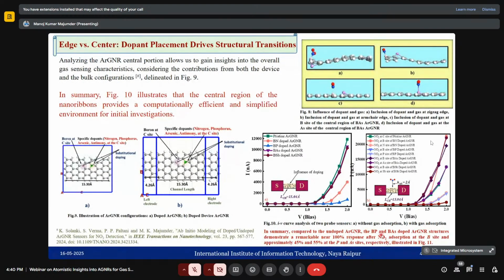In summary, compared to the undoped AGNR, the boron phosphorus and boron arsenic doped AGNR structures demonstrate a remarkable near 100% response after the NO2 adsorption at the B site, and approximately 45% and 55% at the phosphorus and arsenic site respectively. Okay, so this is a very interesting result that we have observed from the QuantumATK software.